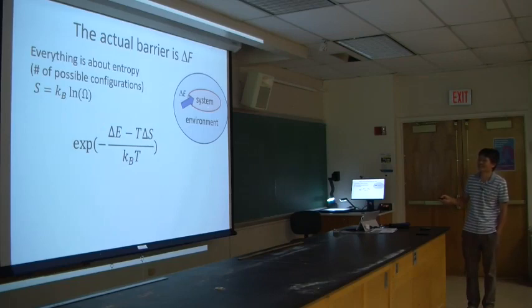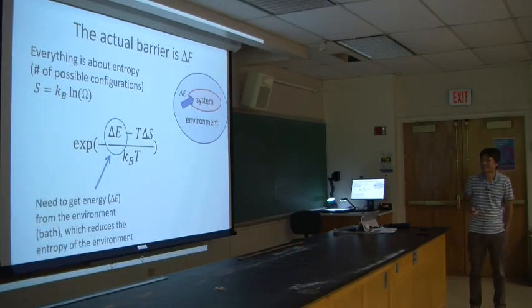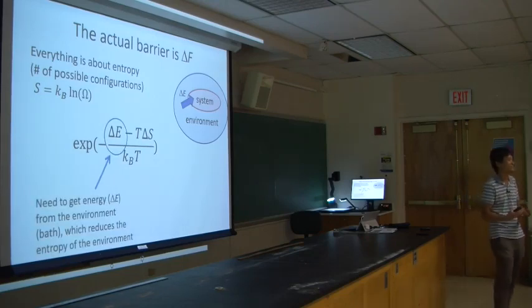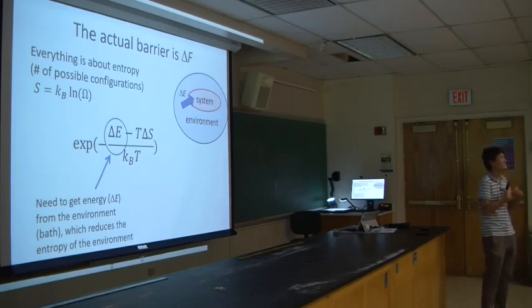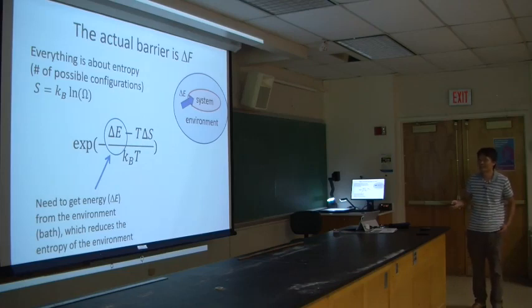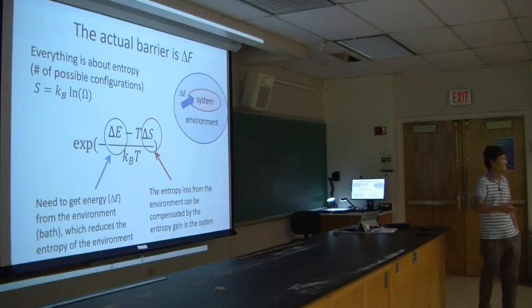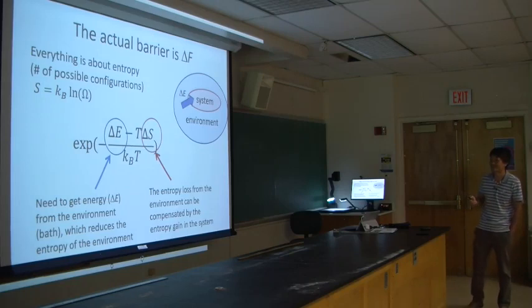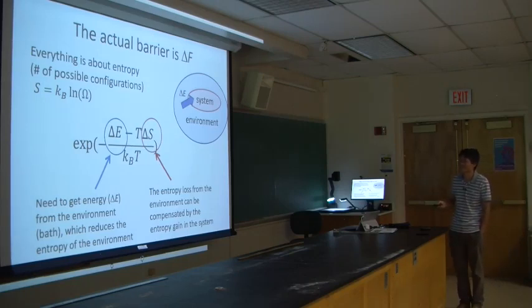You have this kind of term because for an energy uphill reaction, you took some energy from the environment to your system, right? Of course, if you do that, you decrease the entropy of your environment, right? So that's why these things don't happen so often, because you need to wait for the instant when the system takes up that amount of energy, which reduces the entropy of your environment, right? But you can actually compensate for that if the entropy of your system is increased by the energy transfer process, when you have energy transfer from the environment to the system. So that's the delta S we have here, right? You can have this entropy loss from the environment compensated by the entropy gain in the system.